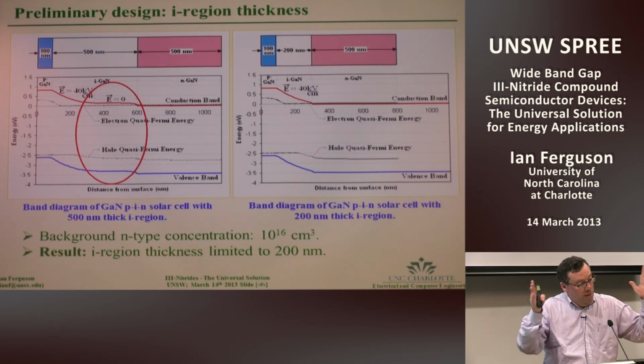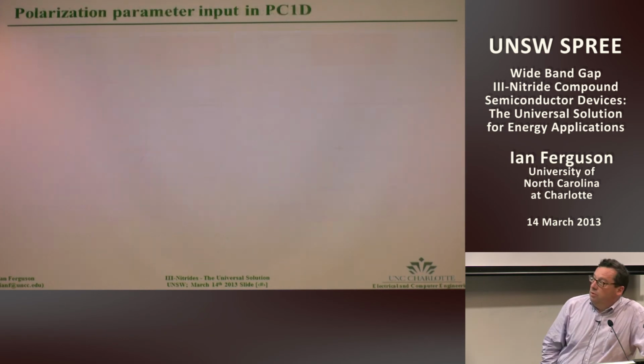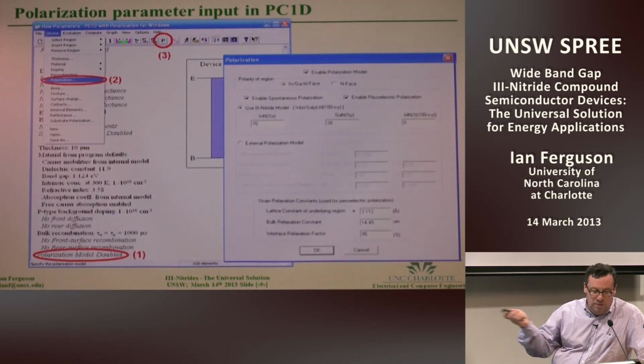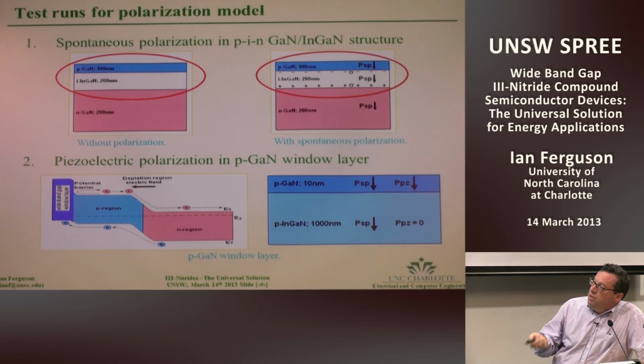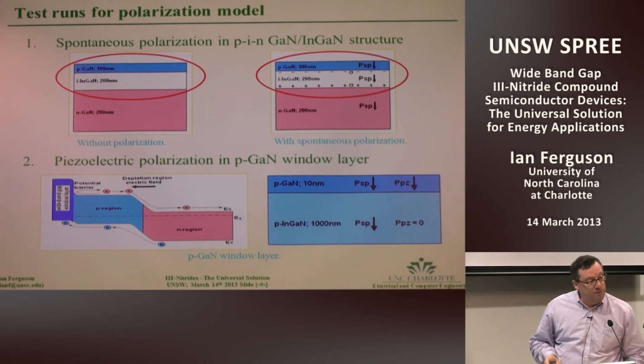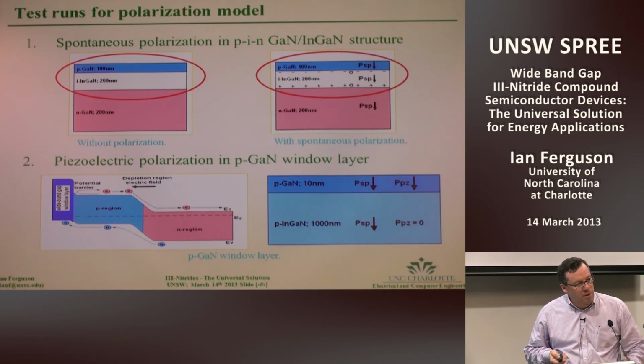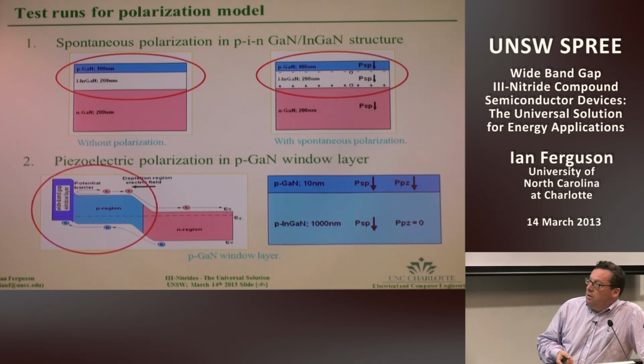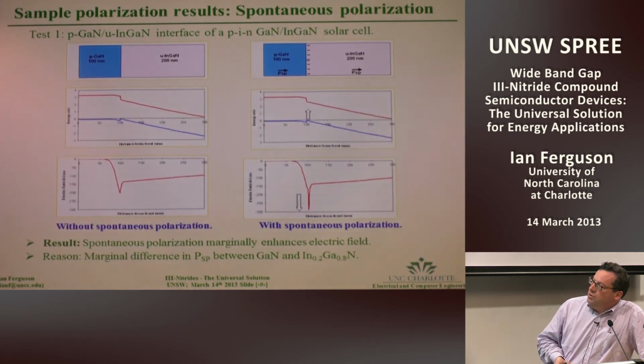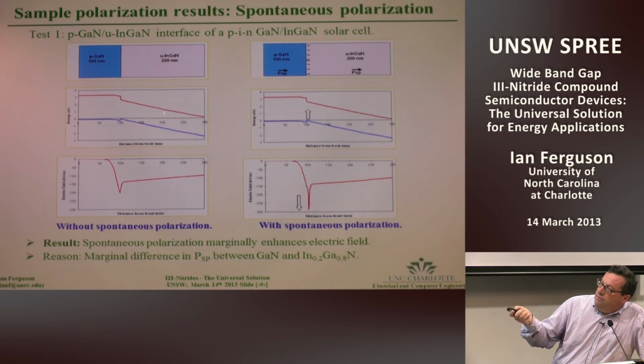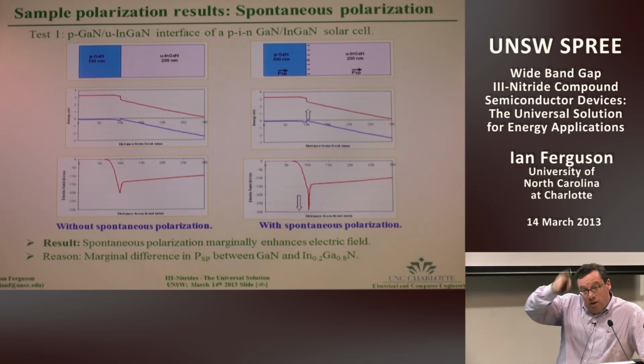This was good in part because it meant that the active regions could be really quite narrow. Then also, as I mentioned, we had to stick in things to address the polarization effects, both the spontaneous polarization and the piezoelectric polarization, which can start producing sheet charge on the surface of the device. So some of the final structures we built were not obvious, in that we may stick a PN junction on the top to pull out this polarization charge and make the device work. It's kind of an interesting area to play around in. And you can see that once you start adding in the polarization effects, it changes the behavior of the band structure, the band edge and your band edge alignments.